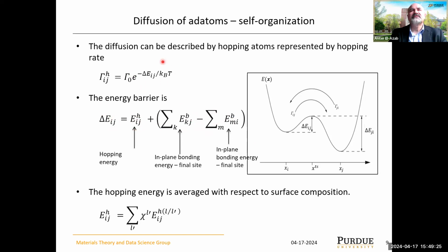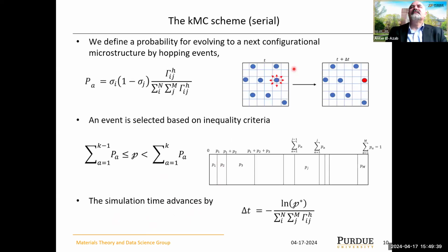A combination gives rise to the hopping rate. And then because of the heterogeneity of the system, this hopping rate and the bonding energies and so on are actually interpolated in terms of the neighborhoods in there. The hopping process looks like this. You have atoms, they have the freedom to move in various directions on the surface. This motion is later constrained by the atomic neighborhood when the surface layer is filled with atoms. So it's a process that depends on the level of coverage of atoms on a given layer.